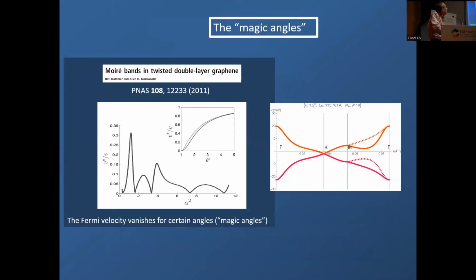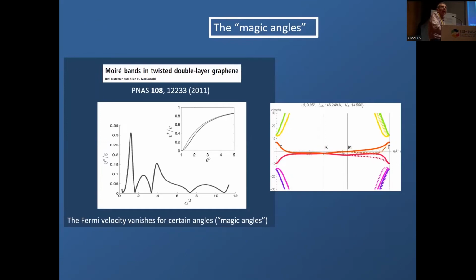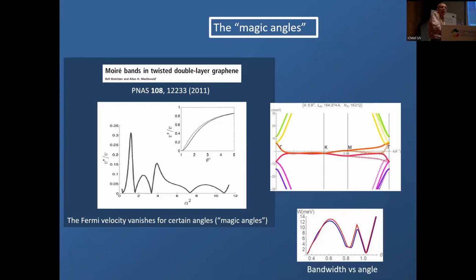So this is one of these narrow bands in twisted bilayer graphene, and this is what happens as you change the angle. Eventually, it becomes incredibly narrow. The width of the band is a few millielectronvolts. And then when you pass this so-called magic angle, the band becomes wider again. So you have to tune a bit the twist angle, and that has been achieved by experimentalists. But if you do it all right, you can have very narrow bands, high density of states, and then electron-electron interactions, electron-phonon interactions can become very relevant.